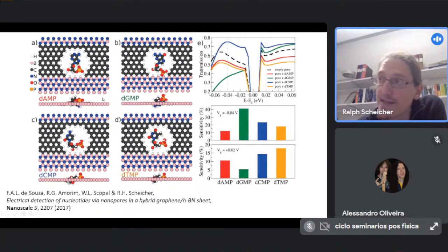So we've done this test, we've done this simulation in the computer. We've put the 4 different bases, adenine, guanine, cytosine, and thymine, inside this nanopore, and then calculated a transmission curve and compared it to the empty pore, shown as this black dashed line here. And in some cases we see an enhancement of the conductance, in some cases we see a drop in the conductance. And we can explain this if we look at the polarity of the side groups of the DNA bases that are facing this atomic wire.